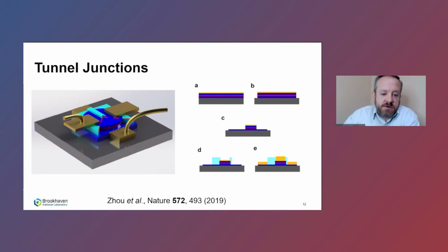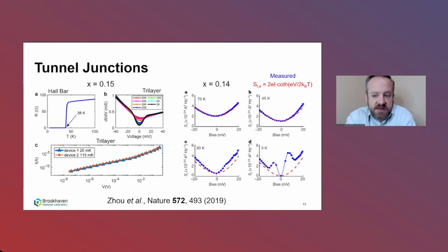Doug Natelson's group is really good at doing noise measurements, so that's one of the things they were looking at. The data I'm showing here on the left in panel A is for a film where the lanthanum strontium copper oxide layers had a doping of 0.15, close to optimally doped. Panel A shows a Hall bar, which was fabricated at the same time as the tunnel junctions, showing that the film had good Tc, good superconducting properties. The differential conductance measurements of the tri-layer are shown in panel B as a function of temperature, and it's clear we have a conductance suppression near zero bias.